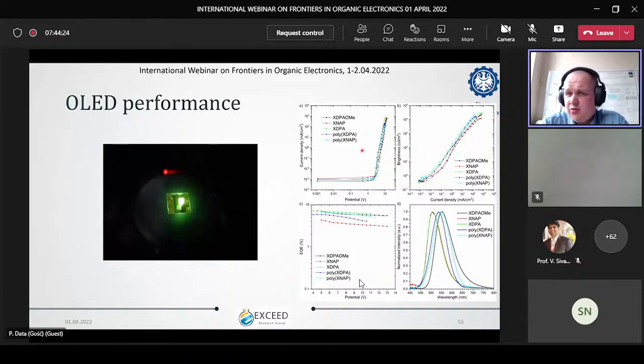So in the end, we made devices, we compared devices from small molecule and the polymer. And what we found out is that we raise our efficiency significantly if we compare the small molecule of the XNAP and the polymer. So it rises like at least 3 times our efficiency of the devices, our EQE.